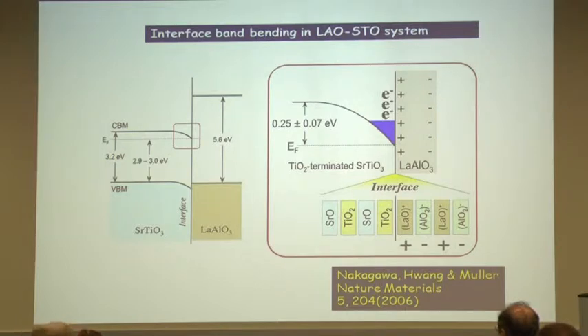The simple explanation for this is the band bending at the interface between strontium titanate and lanthanum aluminate. So the conduction band comes down, crosses the Fermi energy. And if you look at the lanthanum aluminate, as I said, it's a polar dielectric. So you have these charged layers, LaO, AlO2, and so on and so forth. The transfer of electron from here into this triangular well. So the electrons are now confined in this direction along the z direction. But in the xy plane, they are free to move. So you have a two-dimensional electron gas confined along the z direction.